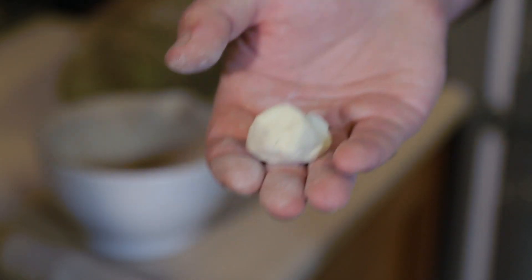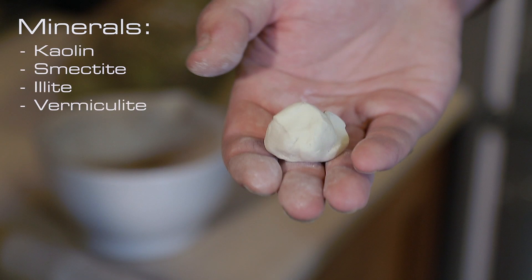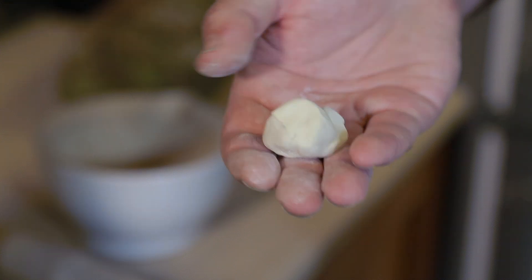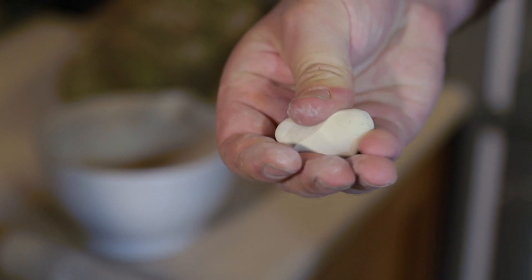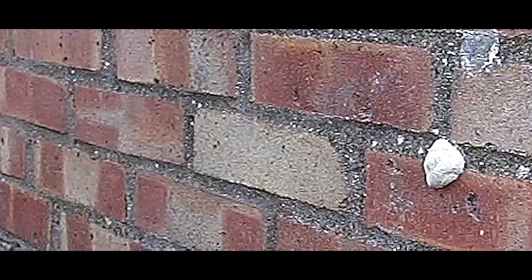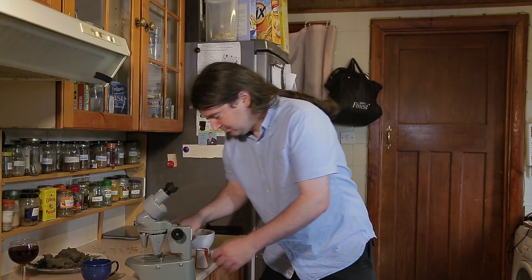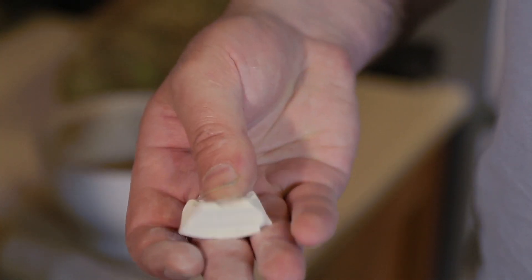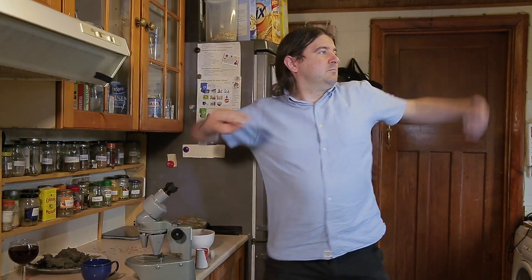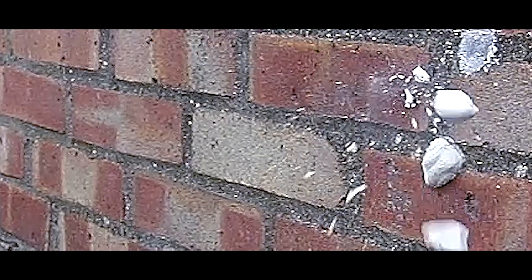Raw clay is made of tiny particles of clay minerals such as kaolin, smectite, illite, vermiculite and impurities such as iron oxides, quartz and magnesium. In raw porcelain, the clay particles are lubricated with water so it is malleable and easy to shape and, on impact, it just deforms. The clay in the air-dried sample is solid and chalky to the touch. Under the microscope, the particles are close together and no longer surrounded by water, so it can no longer deform and is very weak, shattering into dust when smashed.